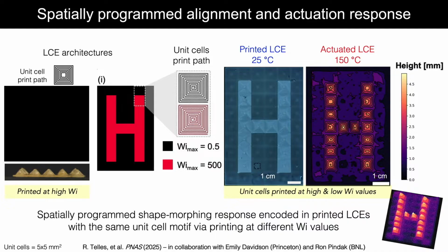For that same material, just by changing the rate of print speed and toggling between a low and high Weissenberg number, we can start to encode only specific regions that will shape morph out of plane. So all of the unit cells that form the H are shape morphing out of plane, and all of the other surrounding unit cells, same design, but at low Weissenberg number where there's really no director alignment, they don't transform. So we have the ability, with the same composition, just by changing something as simple as the print speed, to locally encode, not the composition, it's the same, it's just the alignment, and that changes what regions undergo shape morphing.